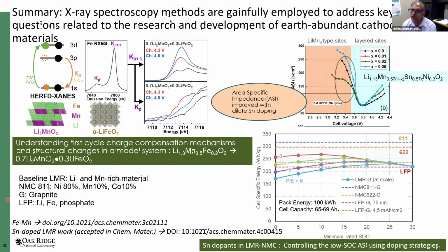It is quite hard to get a good lithium XRS spectra out of these materials. The penetration depth suffers a little bit, and we can get some lithium, particularly when you remove a lot of lithium out of the material. Additionally, in many of these materials, the lithium edge is fairly close to the other M edges. It is certainly very close to that of cobalt, and I have tried to look for it in lithium cobalt oxide. We haven't successfully seen it. We can see lithium in other battery materials, lithium oxygen materials, lithium and electrolytes. We have been very successful in doing that. I know that Christoph at ESRF is also doing such studies. So yeah, I agree, there is scope to do lithium studies.